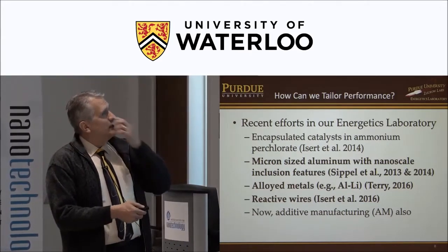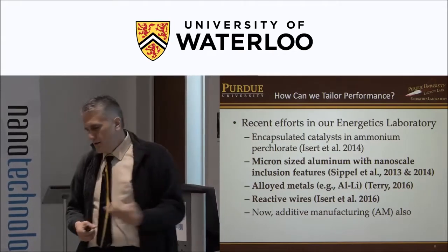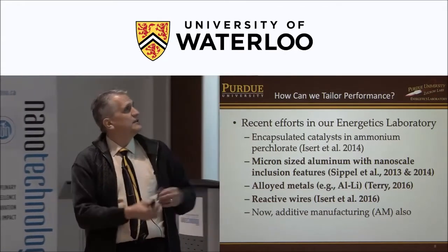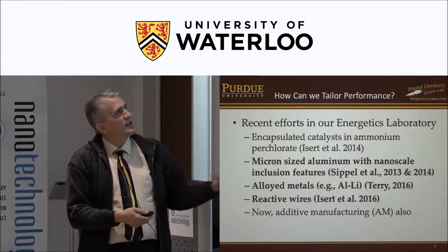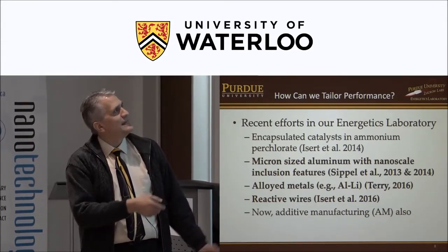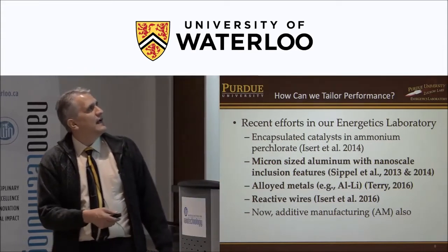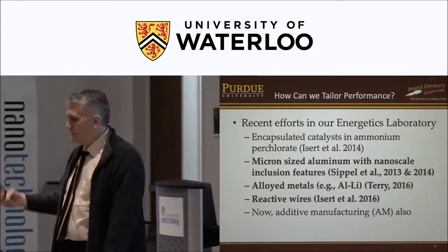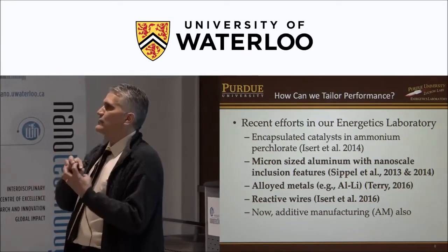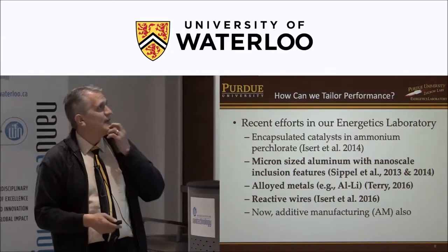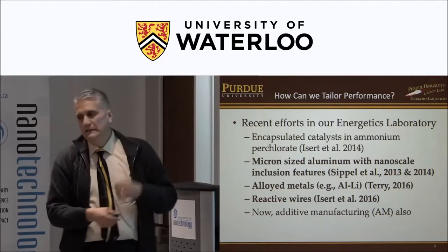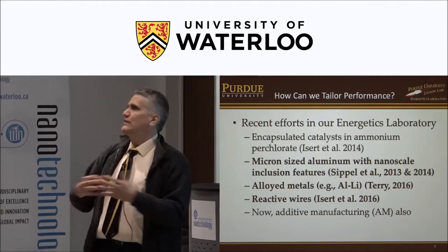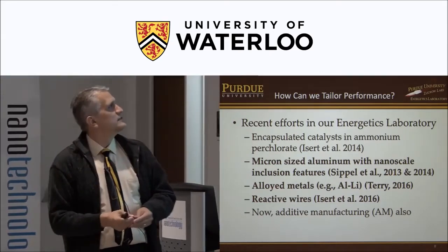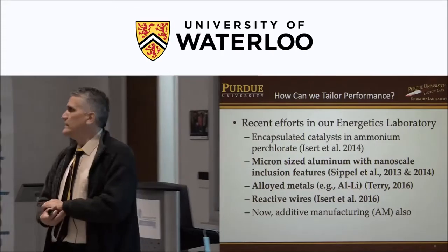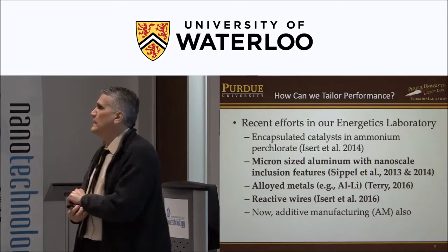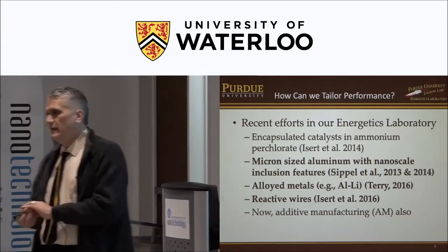We've also looked at, and I'll talk a little bit about this, micron-sized aluminum particles, which is typically used in propellants. Over the last couple decades, people have looked at nanoscale particles added to propellants. But what we did is micron aluminum particles that have nanoscale features. And I'll talk a little bit more about that in a minute. Alloyed metals. So aluminum is used everywhere in propellants, explosives, and pyrotechnics. We looked at an alloyed material, aluminum lithium, because it has some really interesting properties.